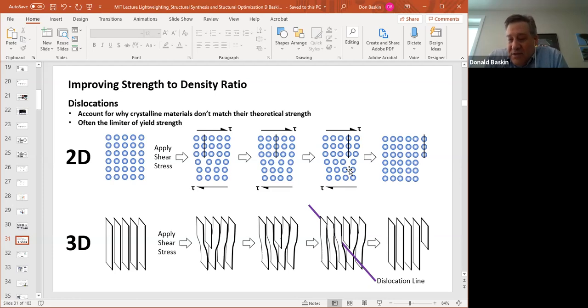In reality, it's interesting. Even though a grain may only be 10 microns across, if it's an equiaxed grain, within a small amount of material, a couple square millimeters, you can have several hundred kilometers, seriously, of dislocation line. That gives you an idea of how small this really is. A couple hundred kilometers of dislocation line in a tiny millimeter by millimeter cube. Think about that.